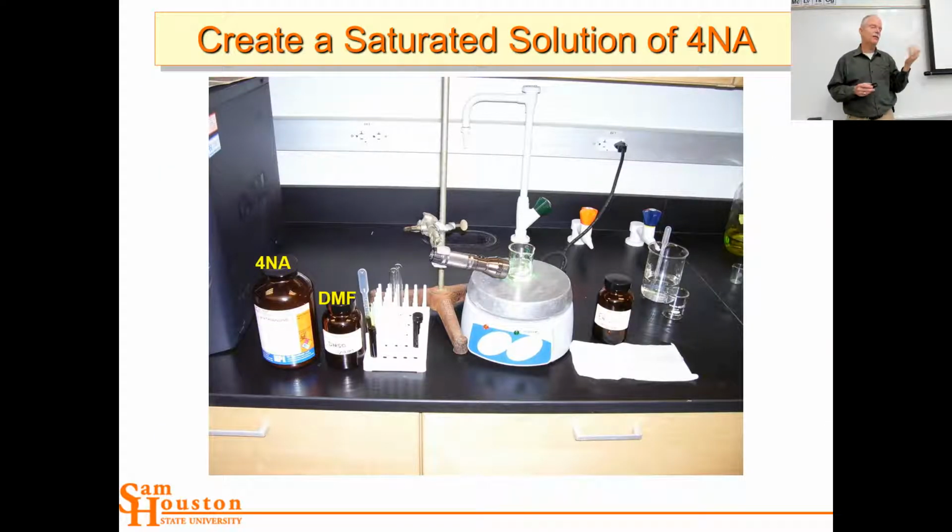So this is our setup, really simple stuff. And we have a light that has a little laser pointer on it. So the laser is shooting through the flask, and we're using the Tyndall effect, scattered light of particles, to tell us when we have precipitation. Although most of the time it was obvious. But in case it wasn't obvious, if we started to see little scintillations of crystals growing, then we would know precipitation had begun. So if you have a homogeneous solution, the laser goes right through